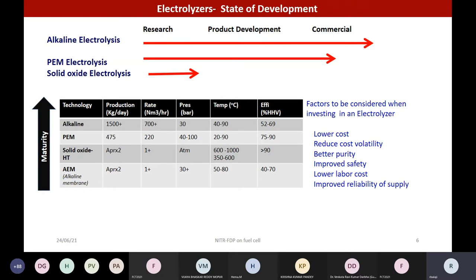But efficiency wise, this polymer electrolyte membrane based electrolyzer technology has a higher efficiency, because, as I said, the hydrogen production rate only depends on the applied current. In the case of PEM, you can operate the system at a very high current density, 1 ampere per cm squared. That current density is achievable in PEM based technology, whereas in the case of alkaline, you cannot go beyond 400 milliamps per centimeter squared. If you operate at more than that, there may be electrode deterioration and side reactions, which will reduce the overall efficiency of the system.